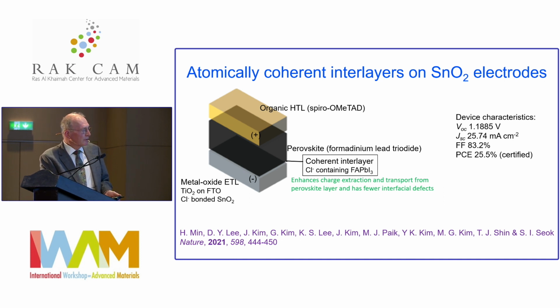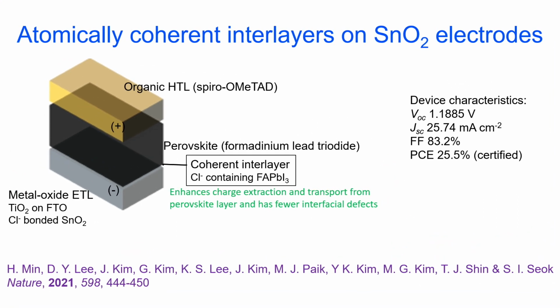This group, a Korean group, described how they modified the negative contact here by titania deposition and then doping that titania with a coherent layer of the formamidinium lead triiodide carrying chloride ions. So that, as they say, enhanced the charge extraction and transport from the perovskite into the electrode. And it also removed interfacial defects.